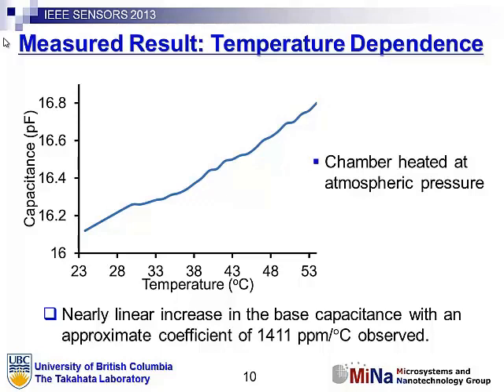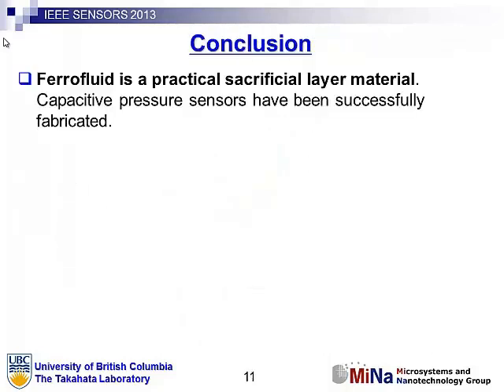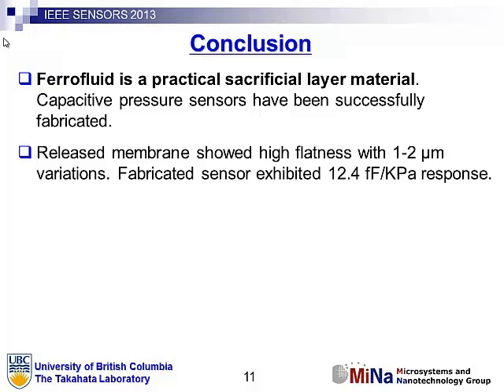So in conclusion, 4 minutes left. Well, okay. In conclusion, ferrofluid was used as a sacrificial material in a surface micromachining type fabrication process, and the sensors worked and showed a linear response with pressure, indicated there. The membranes showed relatively good flatness of 1 to 2 microns over a lateral dimension of 1 millimeter, especially considering the roughness of the substrate was on the order of hundreds of nanometers.